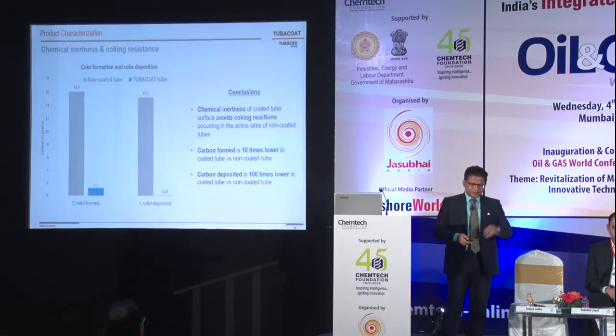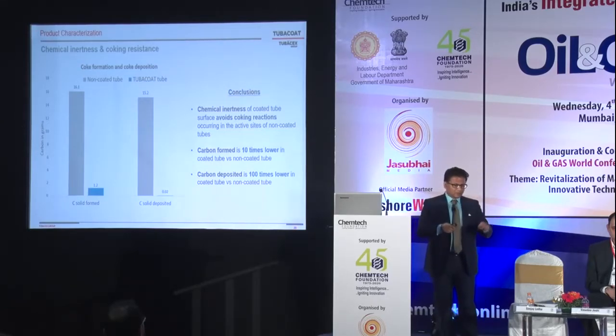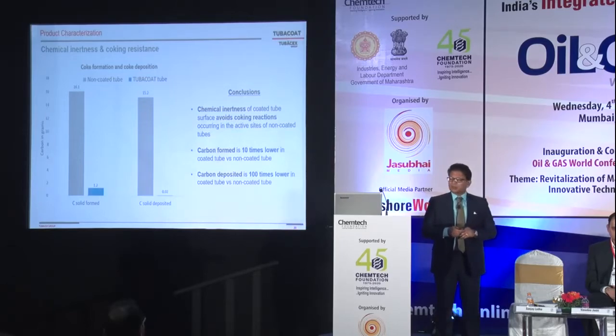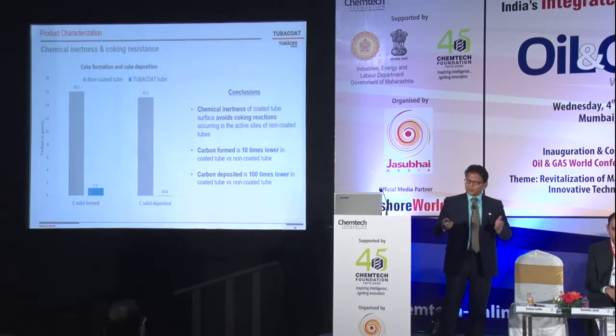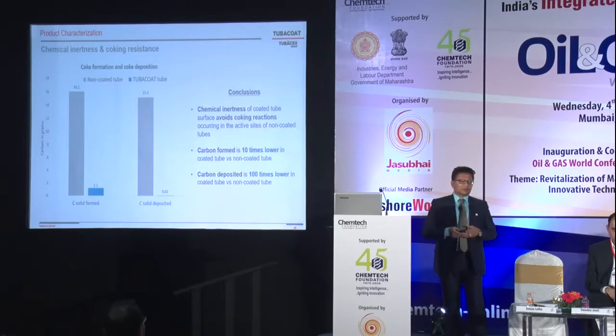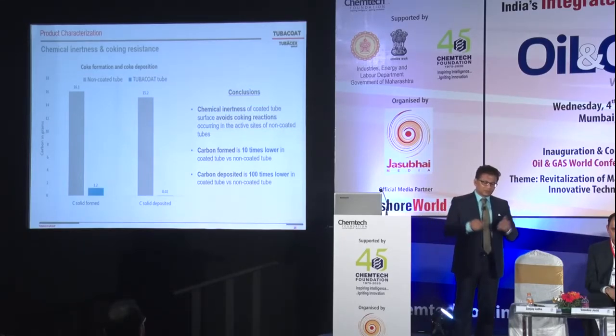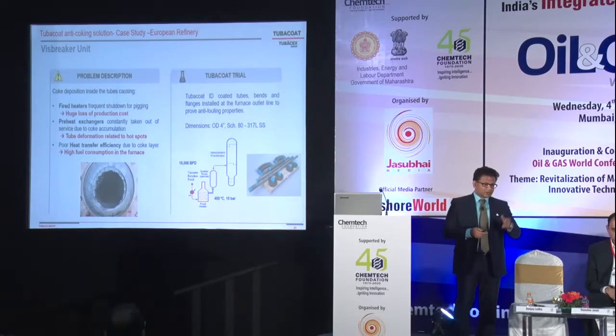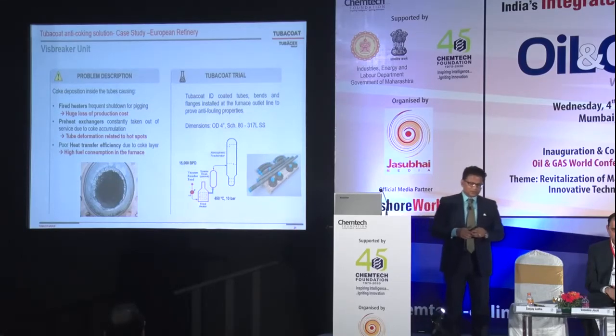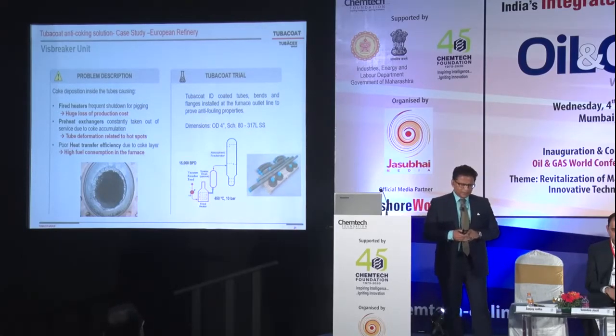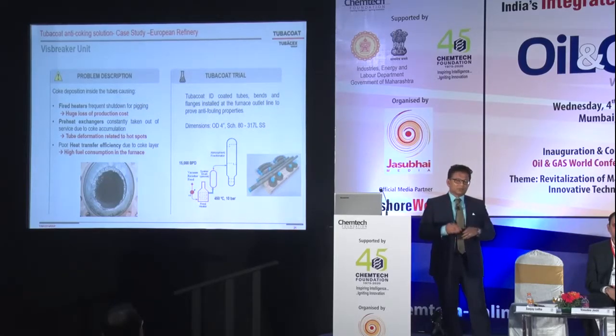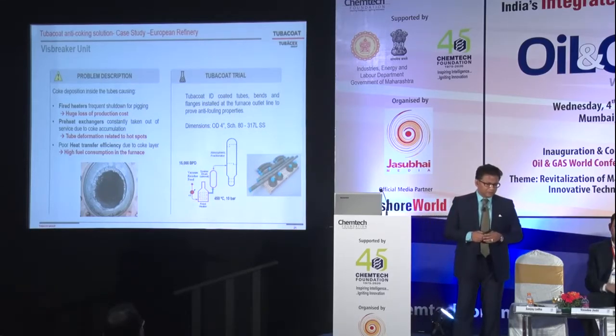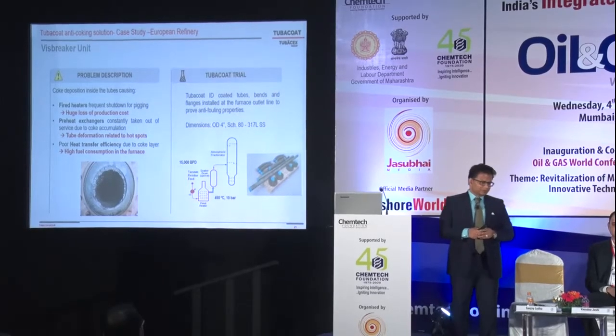So in summary, the chemical inertness prevents the carbon-forming reaction. Carbon formed is 10 times lower, and then carbon deposited in any heater tubes processing heavier feeds such as visbreaker, delayed cokers, thermal crackers, VDUs, the deposition is significantly lower. So one example is this refinery in Europe. 20,000 barrels per day unit, and one day of shutdown for this conversion unit is about $400,000 per day because typical conversion cost is $20. So they have a frequent shutdown for pigging, huge loss for production.